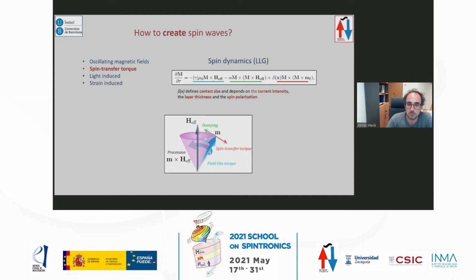So the way to model this is we have precession in blue, we have damping in green, and then we have this additional term, which is the spin transfer torque. So the spin transfer torque, if you look at it, is like an effective damping. You see, it's M cross M cross MF, where MF is the polarization of the current that you use to create this excitation. So eventually, if we do it properly, this beta basically depends on the spin polarization, the current intensity, and many other things. But if you make this have the opposite sign of alpha, where alpha is the damping, in green, right? The spin transfer torque could act opposing the damping.